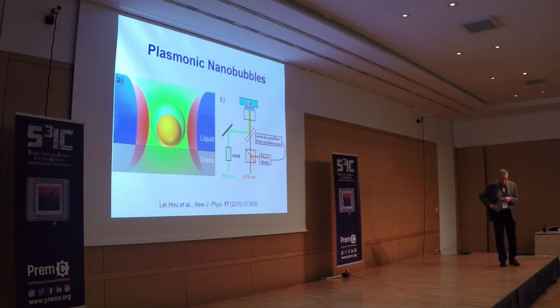Something that I should have mentioned maybe is that gold nanorods are very nice, but they have one disadvantage compared to spheres, namely that they reshape very easily. So if the temperature of the rod becomes too high, the surface atoms start to move, and the shape of the rod changes with time. So you start with a given plasmon, and if you heat too much, the plasmon will start to shift. And if you do it too much, it will become spherical even, and then the plasmon is completely shifted. So that's why we have to go with spheres, because we want to heat a lot, and spheres are not readily reshaped like rods.